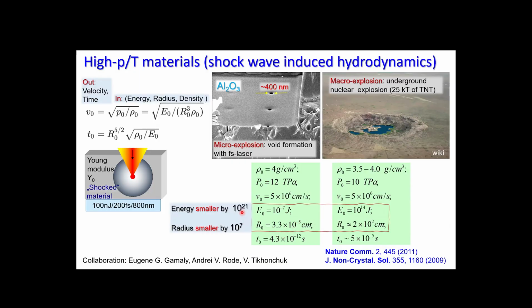It has 21 orders of magnitude larger energy, so this is a 25 kiloton nuclear explosion. And it's triggered with a size of 2 meters in radius, so it's kind of rocket bomb size, which is 7 orders of magnitude larger than our radius, which is deposited. So this is 21. This is 7 orders of magnitude because the cube is sitting here. Hydrodynamically, these two events are defined by the same scaling.